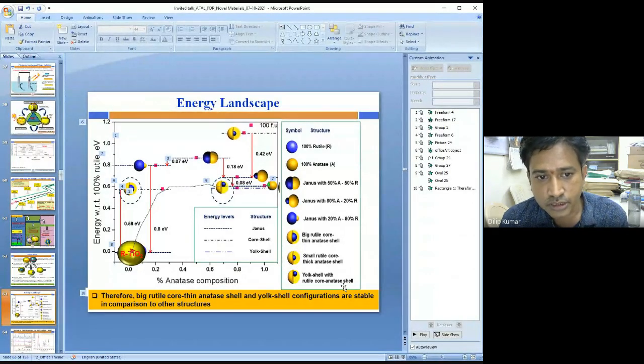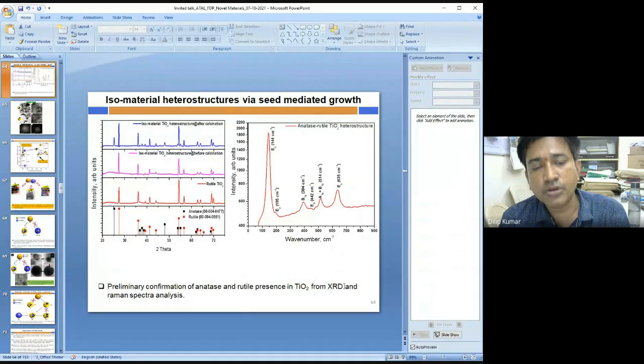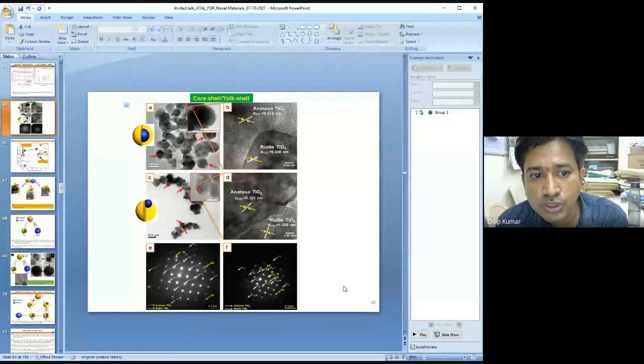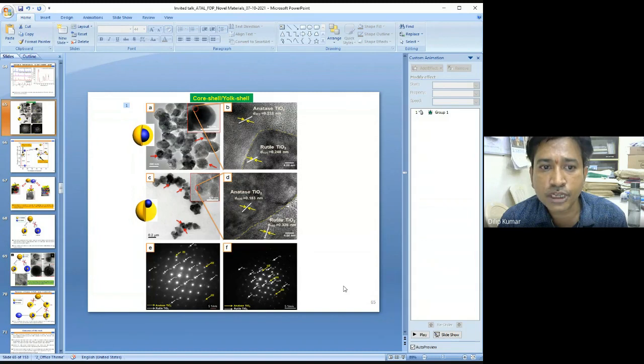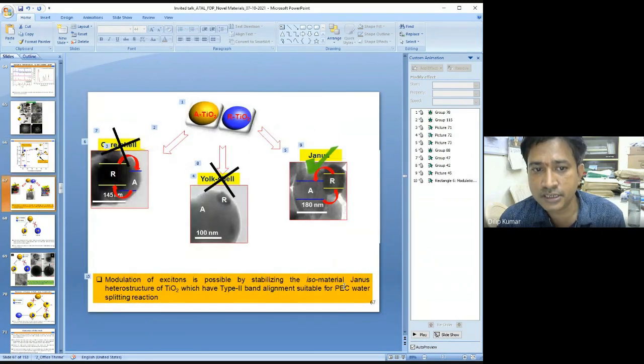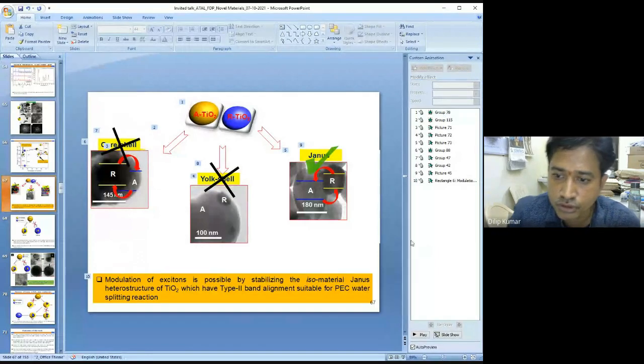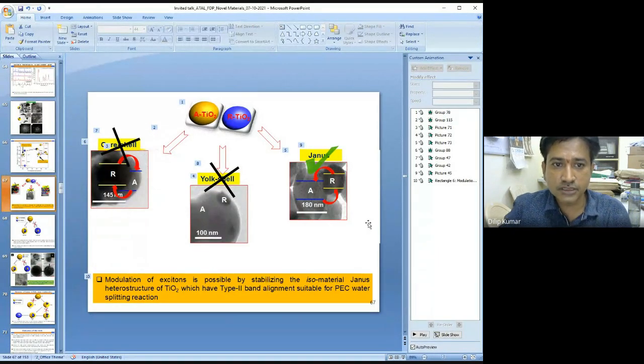So after all, what I got is, I could make the material what we call iso-material heterostructures, and I synthesized it in my lab, and I ended up with some important structures with core shell and yolk shell, which have been confirmed with high resolution transmission electron microscopy images. And whatever the computations told and whatever the experiments revealed, both are matching. And this work gave me a lot of confidence in understanding photoelectrochemical water splitting efficiencies. Because if you look at these three structures which I have prepared, either core shell,